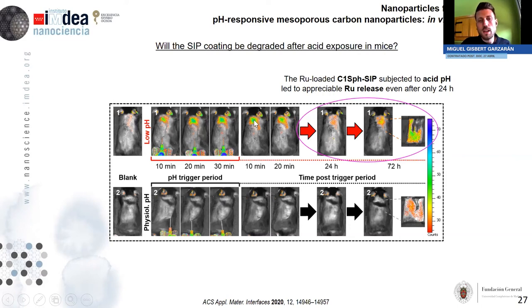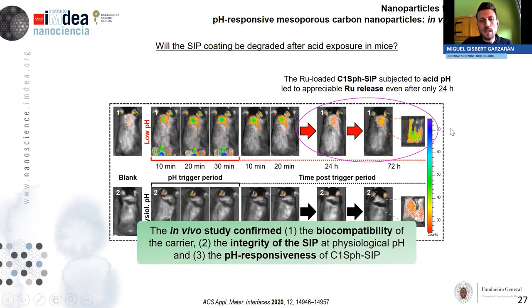However, when we have this acid pH, the polymer self-immolates, the pores open, and then the payload, in this case the ruthenium dye, can be released. So in summary, to finish with this part of the talk, we can conclude that these kind of SIP-coated nanocarriers are biocompatible. Also that this self-immolative technology is strong enough to be administered to an animal and remain unaffected without undergoing self-immolation. And also that if we subject this material to an acid pH, it will release the payload.